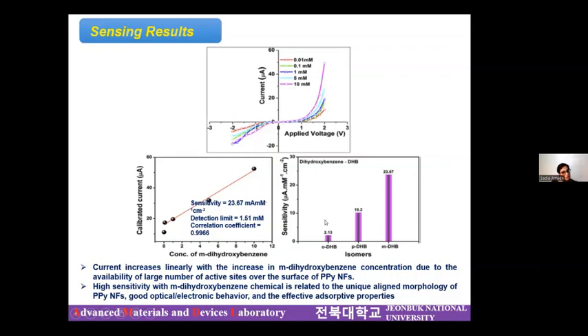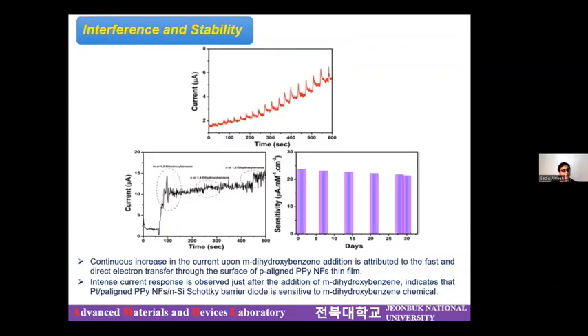And apart from meta-dihydroxybenzene, we have also performed the sensing in the same solution for its isomers, like para- and ortho-dihydroxybenzene. But we found that our synthesized sensor is capable of detecting meta-dihydroxybenzene the most as compared to its isomers. And from this, we have also performed the stability study. Stability data means we just wanted to know how long our sensor is stable at ambient conditions. So we performed the sensing experiments for 30 consecutive days, but as you can see from the histograms, it didn't show any specific deterioration. That means our sensor is sensitive as well as stable under room temperature conditions.